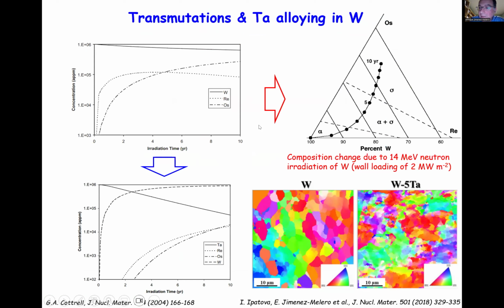Now you may think, why is this important? If you look at the phase diagram, if you start with the alpha tungsten phase, as you start to form more rhenium and osmium, you go into the alpha plus sigma phase. And that sigma phase is brittle, so it will become more brittle over time.